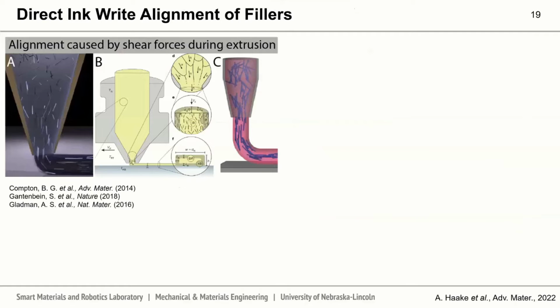Through looking at literature, we see that alignment can be caused by shear forces during direct ink writing if the ink includes high aspect ratio fillers. These fillers align as they move through the nozzle.